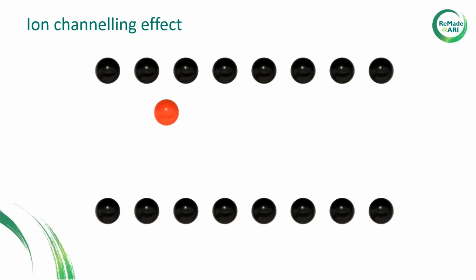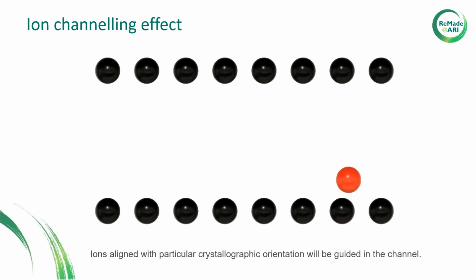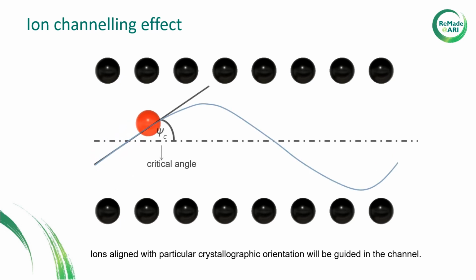RBS is measured in a random direction, but if the incident ion beam is aligned along a particular axis of the crystal, the ions will be guided in the channels formed by lattice atom string potentials. These ions cannot get close enough to the atomic nuclei to undergo large-angle Rutherford scattering. They will be subjected to small-angle screened Coulomb collisions with the maximum critical angle, and they will penetrate into the crystal. This effect is called ion channeling, and it can be applied in RBS analysis in the channeling mode.